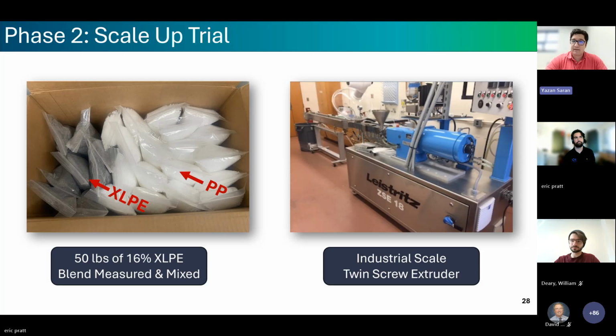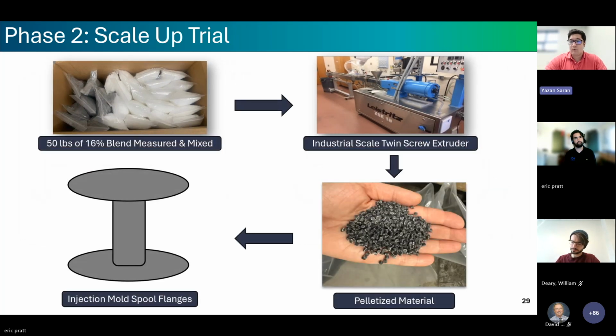So after a week-long process of sieving out and mixing our bulk sample, we sent it out to our partner for industrial scale twin screw extrusion, compounding, and pelletization. The compounding trials were performed under the same parameters that we use when we compounded our blends in-house at our Holden labs and were a large success, meaning that we could move forward in delivering on our molded spools. We received a small portion of the pelletized material back for further characterization and testing, while the rest of the 50-pound bulk sample was sent to our injection molding partner, Vandor,